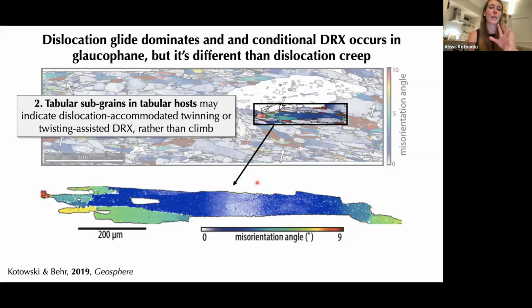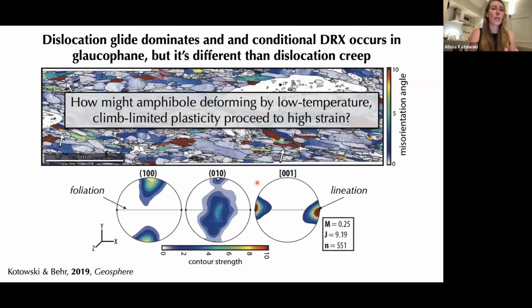This is also consistent with the fact that these rocks are deforming under lower temperature conditions. So we have more difficult diffusion, more difficult recovery. So if these rocks are to produce dynamic recrystallization, it would probably be by a different mechanism than conventional dislocation creep. So the question then is similar to what we raised for the rocks from Oman. If this is the case, if we have a climb-limited plasticity mechanism dominating this microstructure, how can this amphibole actually proceed to high strain? How can this rock accommodate more strain? And what is going to allow it to do that? And could that mechanism potentially also be consistent with creating a slip transient?